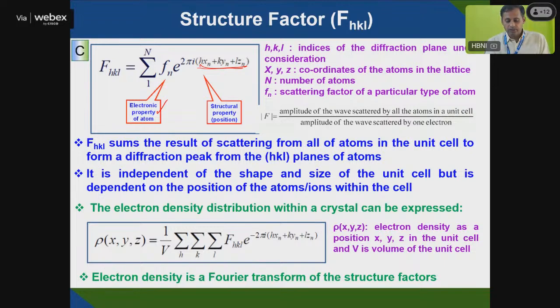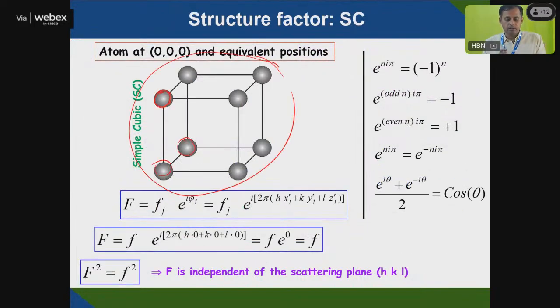So the total amplitude of the wave scattered by all atoms of the unit cell divided by the amplitude of the wave scattered by a single electron, that gives you the whole structure factor. You can find out the density by dividing by the total volume. Then if you calculate the structure factor for simple cubic, these are some of the equations taken into consideration.